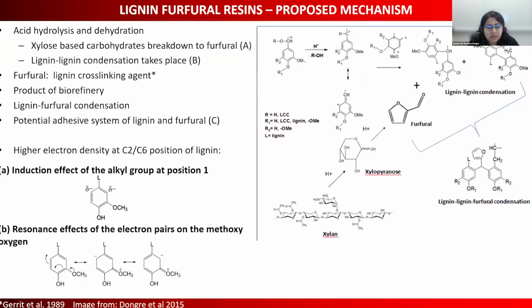So the concept behind making the lignin furfural resins was as follows. The lignin that is isolated from the hot water extraction process contains some sugars. The idea was to make the resins in acid conditions, which would break down the xylose present in the lignin to furfural, and also cause some lignin-lignin condensation, as you can see here in the diagram, and form either a lignin-lignin condensation product or a lignin-lignin furfural condensation product. So the furfural would act as a cross-linker to bind the lignin molecules.